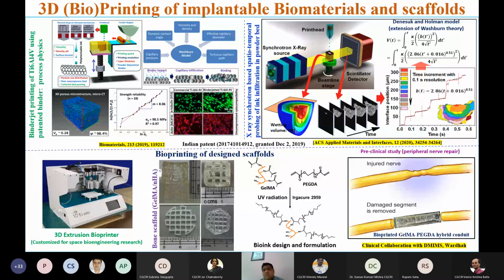To take this work forward, we have done an X-ray synchrotron study at the Diamond facility in the UK, and that allows us to quantitatively analyze this infiltration kinetics, both in space as well as in time. And we also extended this Washburn theory, particularly to incorporate the Denesuk and Holman model to find out what the wetting volume is and how it increases with time of interaction.